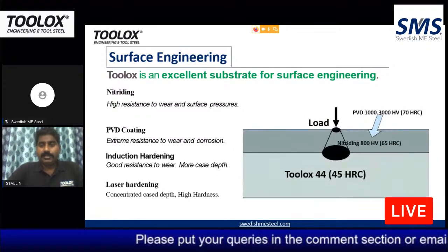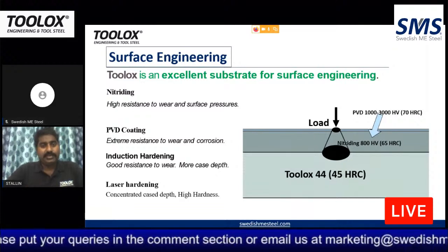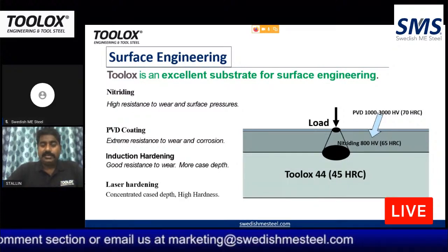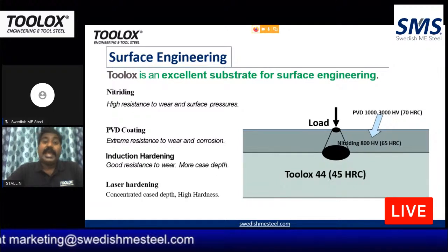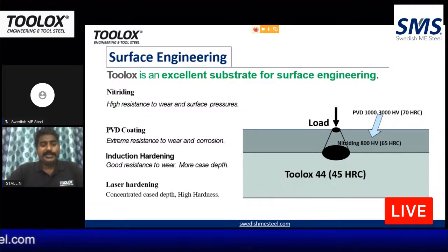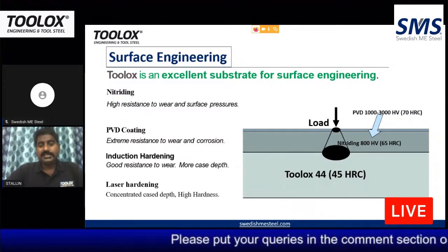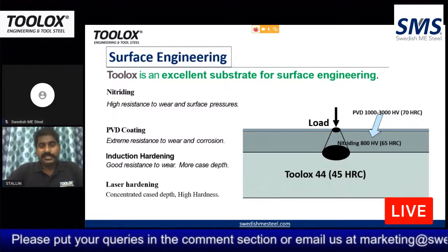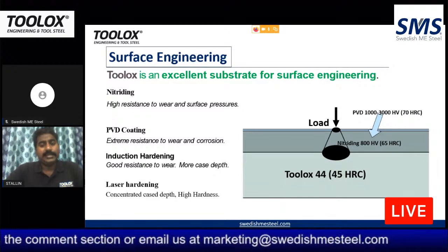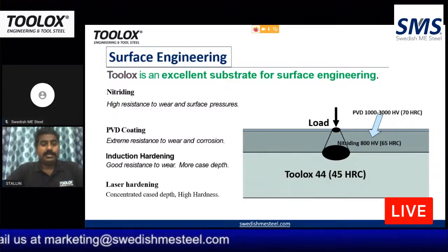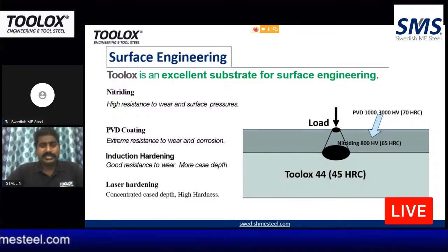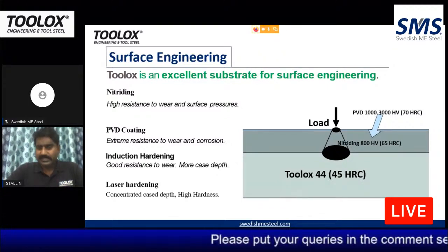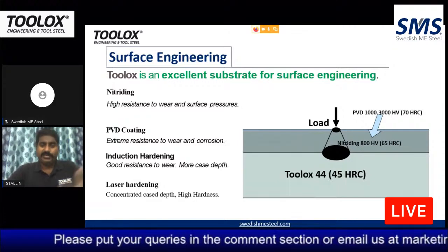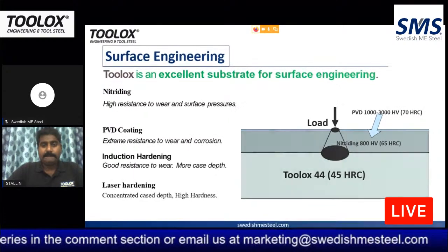So you have a base material at 45 HRC which has very high toughness as well as strength, and adding to that it has a tempering temperature of 590 degrees centigrade, and we don't think any surface treatment process requires more than 590 degrees centigrade. So this would be more than enough for you. Nitriding can achieve 60 to 62 HRC, PVD you can achieve 70 plus, and induction hardening you can achieve 50 HRC. We'll see what hardness each of the processes will achieve.